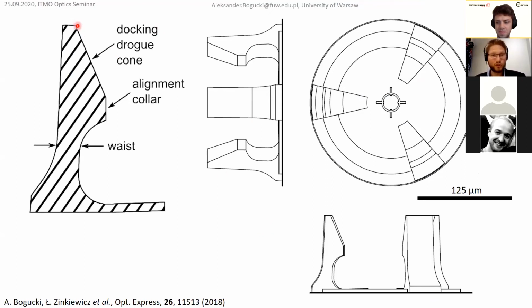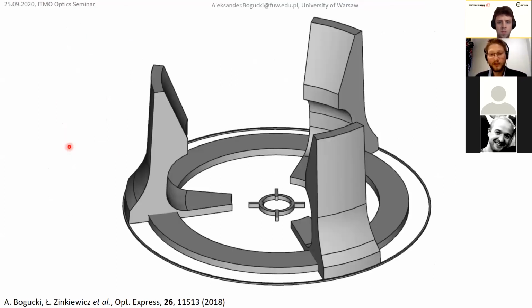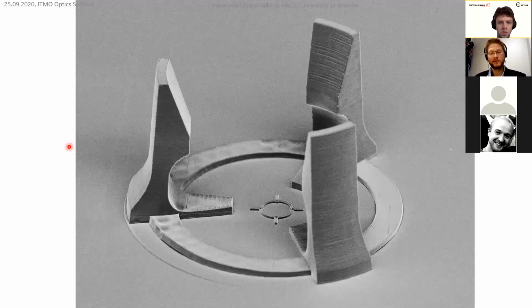We call this a docking drogue cone, alignment collar, which is in diameter 125 micrometers, so the typical optical fiber. And here is the waist, and by tailoring this waist size, you can tailor the stiffness of your spring. So this is our CAD design, and this is our printed result. As you can see, they are in agreement.